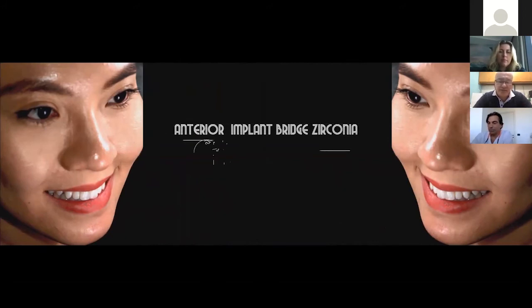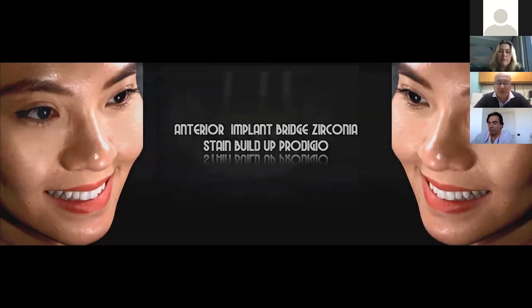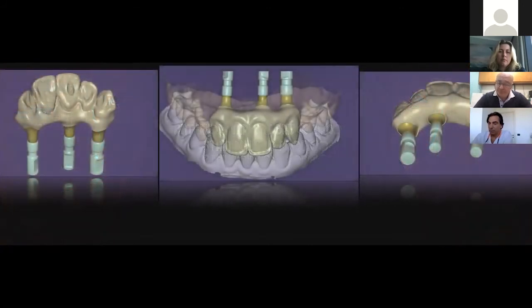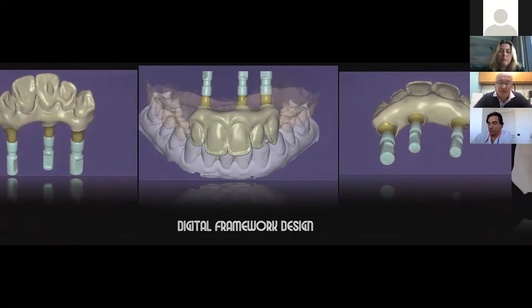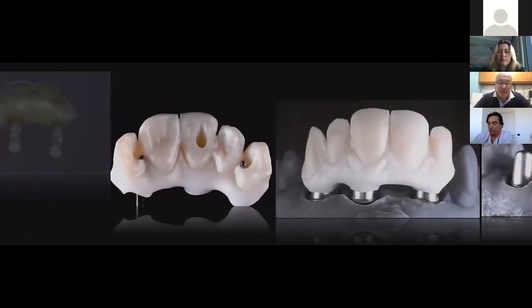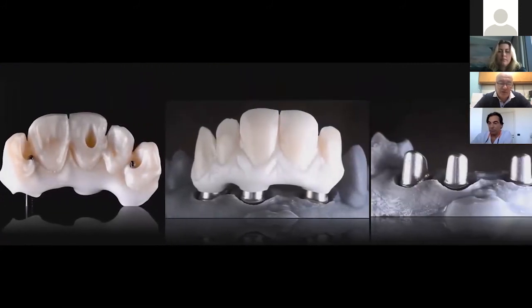This is a very simple case. It's an anterior implant bridge in zirconia. A minimum layering of porcelain has been used, but mainly the stain buildup Prodigio was used on top of this buccal layering. It's a 5-unit on zirconia, 3 implants, in an anterior case. Of course, we do all the digital workflow to create our framework design. And after we are ready with a custom abutment and zirconia, we can also have zirconia pure color, which could be A1 or A2.